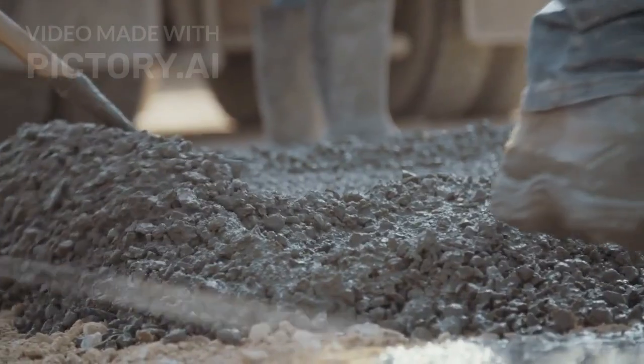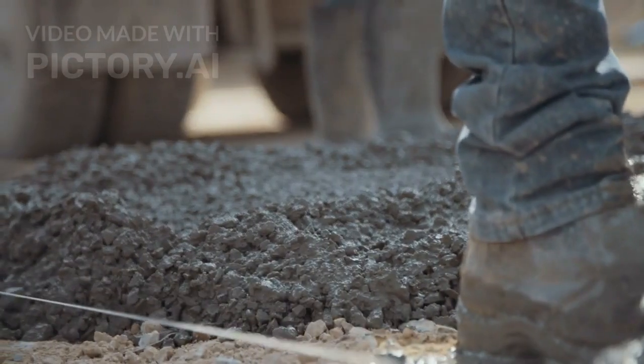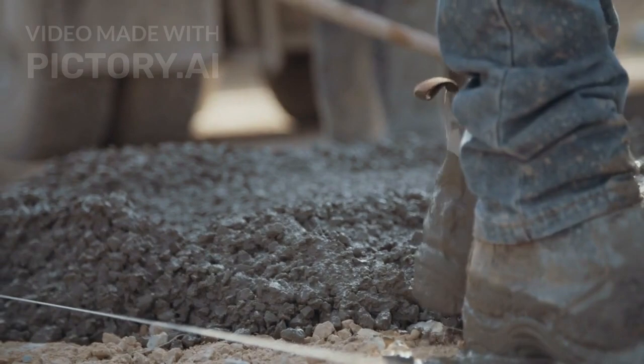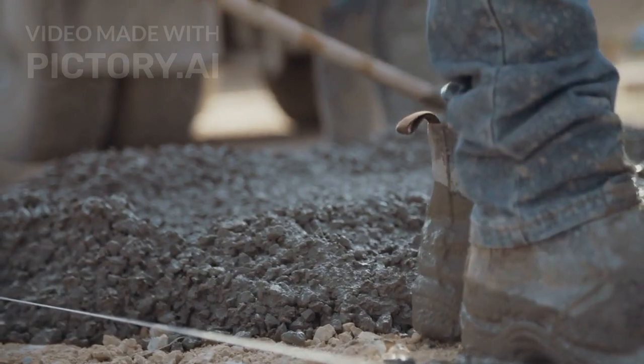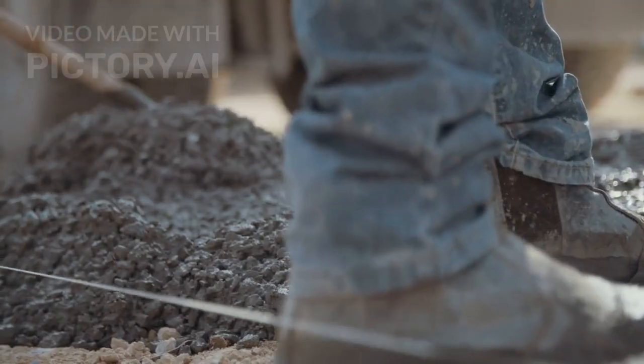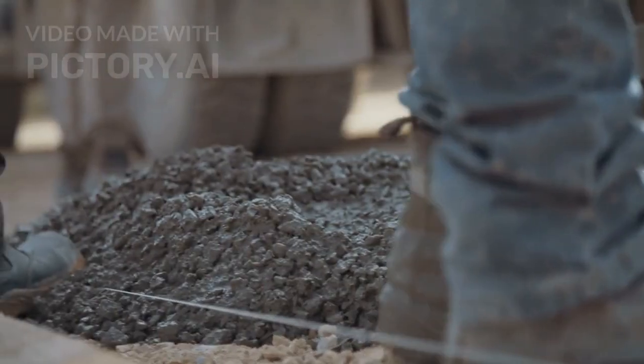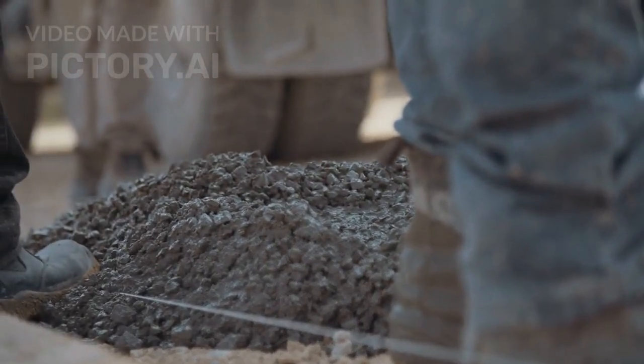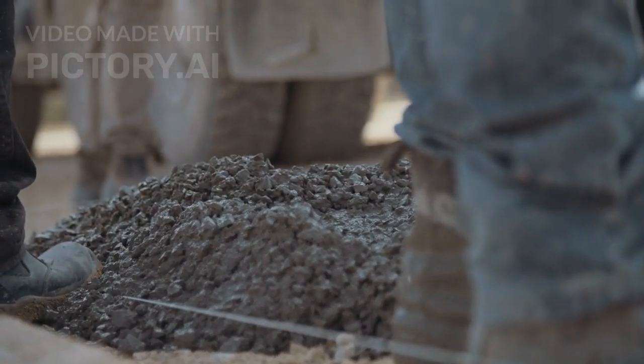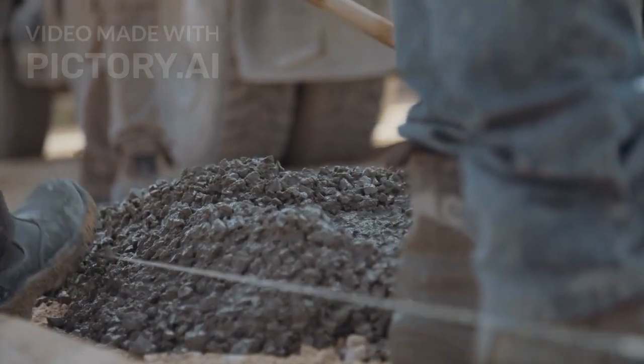That's genuinely impressive, especially when you think about how simple the ingredients are. Yeah. Starch and dirt. And the relatively low energy process, too, compared to melting rock, for instance. Right. No extreme temperatures needed, no super complex machinery. And crucially, most of the water used in the process can be recovered, because the binding relies on dehydration, drying the starch paste out. It's not like cement where the water becomes chemically locked into the structure, so you can potentially reclaim a lot of that precious water.